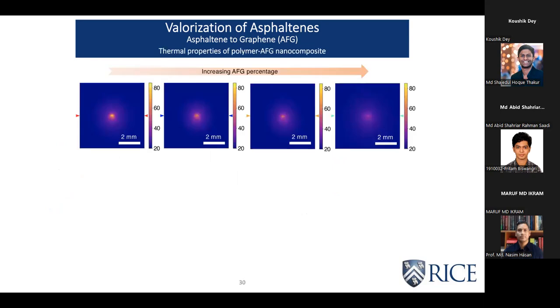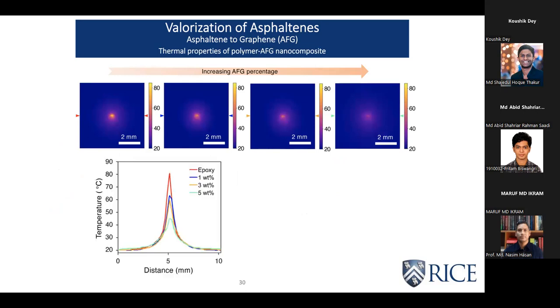Next, we investigated the thermal properties. Basically, we took the composites and shone a laser light on them, and we recorded the temperature using an IR camera. And as you can see, with increasing amount of graphene content, the maximum surface temperature is reducing.